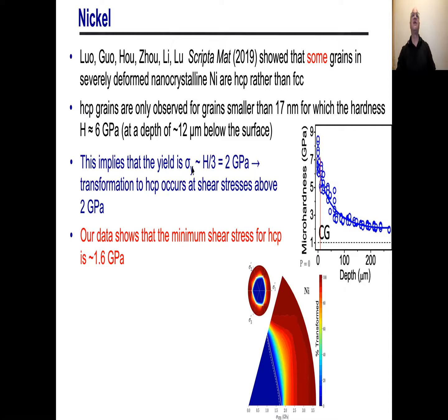If the yield stress is about the hardness over 3, sort of typical values you use, that suggests that the stress is about 2 GPa where the transformation occurs. It doesn't mean that the stress is actually 2 GPa, but it can be as large as 2 GPa up to the yield strength. Okay, so it would seem to suggest that the FCC can transform to HCP for shear stresses above about 2 GPa. And if you go back to the curves here, this transformation actually starts at 1.6 GPa according to the DFT calculations. So that I'd say is remarkably consistent. You know, within a factor of 2, I would say it's probably good enough, but that's like 20% kind of value. So pretty good agreement.